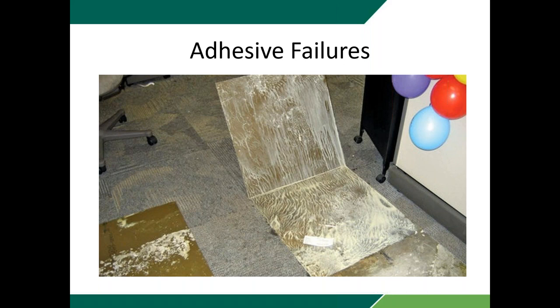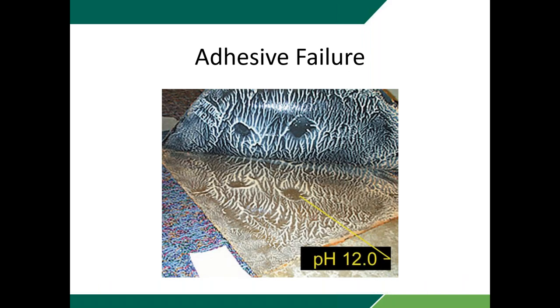So when we glue down carpet, tile, those kind of things, and we don't control the moisture coming up out of the concrete or in the concrete, then we can end up with a breakdown of the adhesive and a failure of adhesion. Another thing that happens with a lot of these adhesives is they're not very resistant to high pH levels. And when we're dealing with concrete, particularly wet concrete, the pH levels can get to be fairly significant. You get a pH of 12 or so, and it starts to break down these adhesives, which leads to, again, adhesive failure.